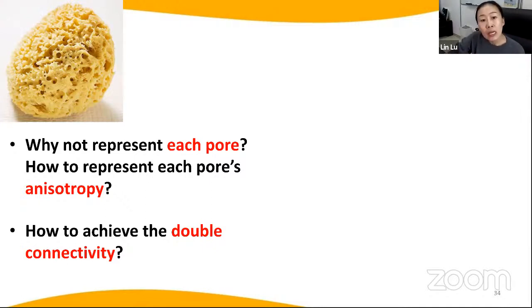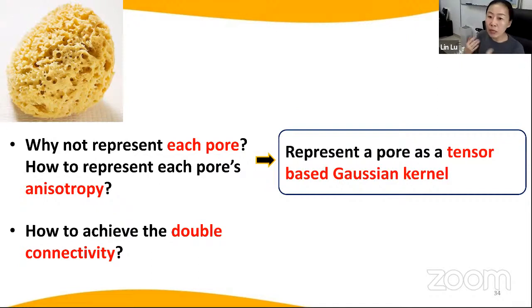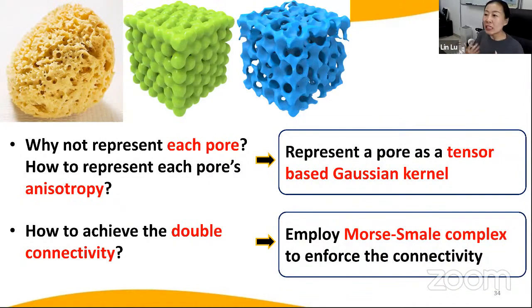For the first question, we propose a tensor-based Gaussian kernel to represent the pore instead of the solid. For the second part, we really need to have the guarantee, so we employ the Morse-Smale complex to enforce double connectivity. As shown here, we first model the green part, which are pores, and then simultaneously we get the blue one, which has a porous structure. That's the idea and also the motivation of this work.